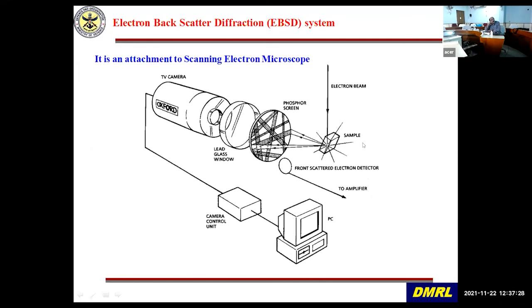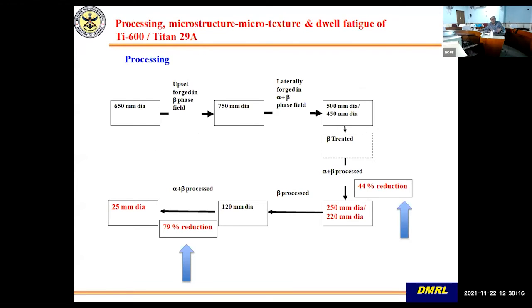Now, for knowing the orientation, nowadays what you have is EBSD, electron backscatter diffraction. It has become very easy to know the orientation. Grain wise, you can focus and see what orientation it is, and you can get an orientation map. This is an attachment to a SEM, scanning electron microscope. It has got a camera, and when you orient your material properly, it can generate Kikuchi bands. These are from basically planes which are there in the crystal of your material, and these can be indexed. Very mathematical formulations are there. These can be automatically indexed and give you the orientation of each grain, how it is oriented. I will show you an example. And why we are talking about this, because we are bothered about the mechanical properties ultimately.